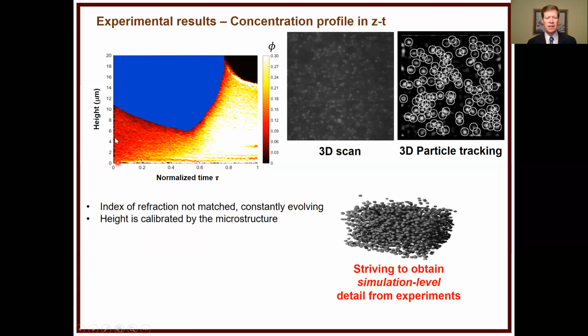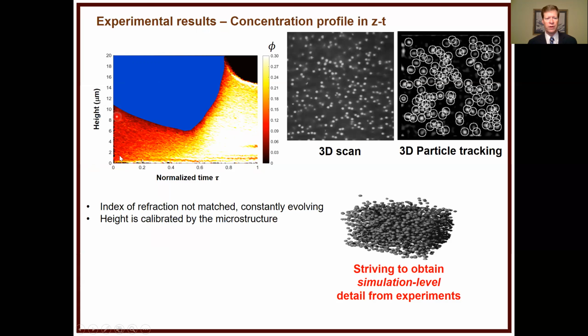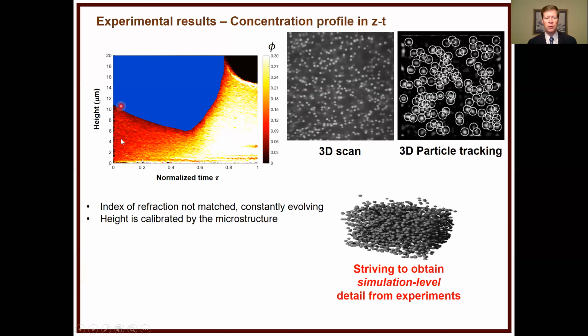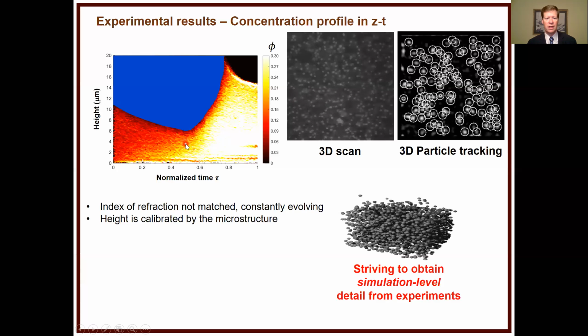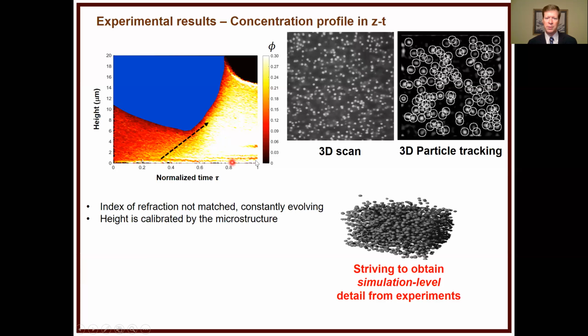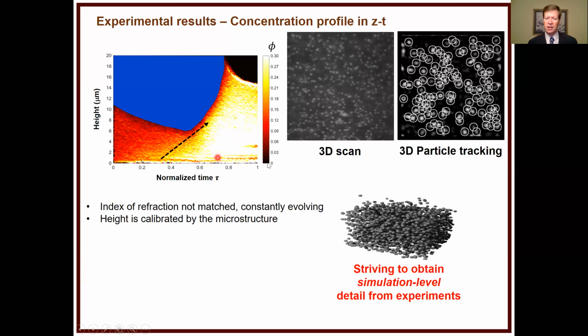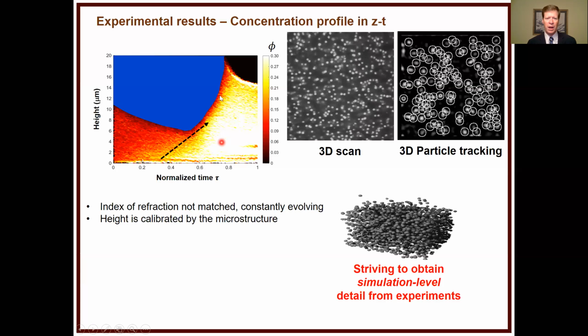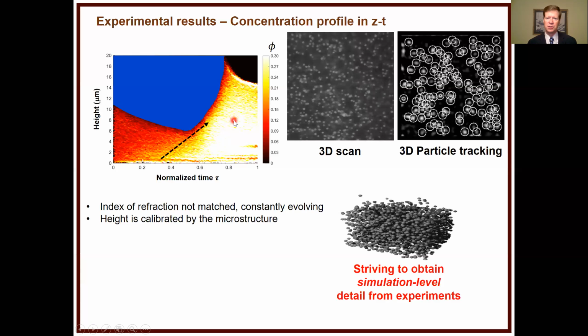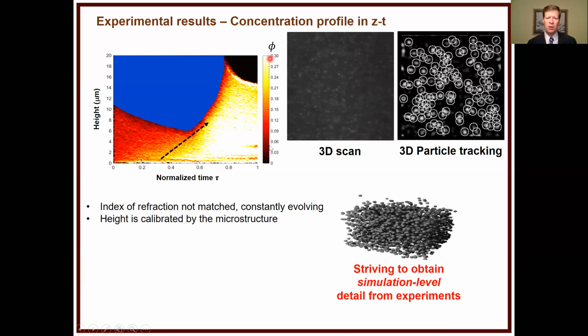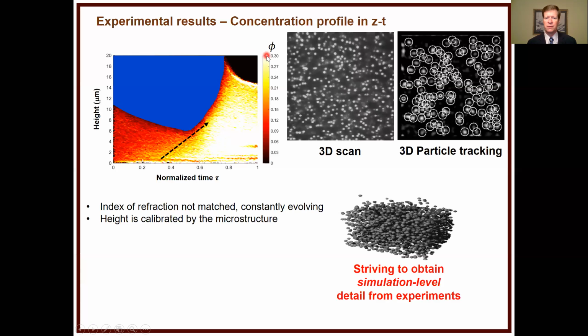What you can see is at the beginning, this is for pH 7.5, we have a relatively uniform system. Then as we go in time, there's a little bit of sedimentation and a little bit of structure near the bottom surface because those colloids start to order and crystallize. There are no drastic fluctuations in concentration. The colors now are 0 to 30%, if that's hard for you to read.